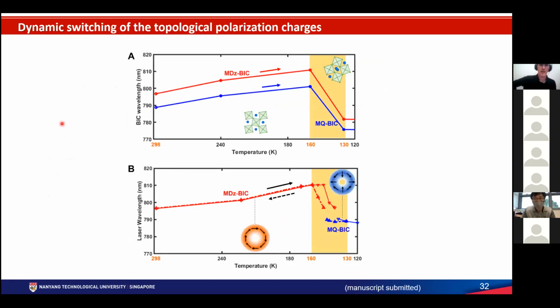If we follow the emission through the whole cycle of temperature, simulations show that both modes actually shift. But thanks to the gain loss overlap, what we observe in the lasing regime, while in the PL you will observe both of the modes, is one mode when you start cooling the structure. It continues to persist even when you go into the transition region, and then it switches to the other mode, the magnetic quadrupole BIC. Then it stays until you continue to cool, and when you go back, you show retentivity. So in the end, you create a dynamic switch between one and the other. You can have a single temperature where you can switch dynamically between the emission with one polarization vortex singularity and the emission with the opposite polarization vortex singularity.